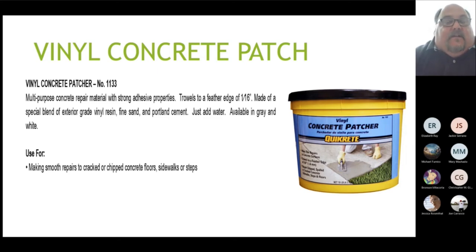But just remember that with some of these hairline cracks, you need to get material in there. So you're going to have to open up the crack so you can get some of this material in there, because trying to cram a sanded cement product down a hairline is not really going to work. There's not enough material there for it to work. Same things apply. Make sure it's clean, make sure it's damp. Go ahead and push it down in there and then screed it off and walk away. And it's a great patch.